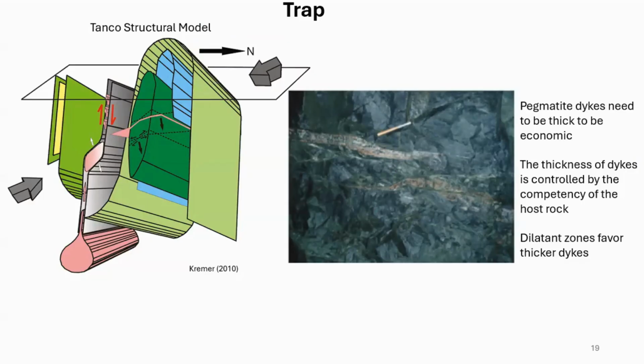We have structural traps. So this is a model of Tanco that Paul Kramer did. We can see these nice en echelon dikes cross-cutting a gabbro raft in Tanco, and the model is that it's transpressional and you're getting opening up in a particular band of the shear zone, similar to what we see as a dilatant zone in gold deposits. So there are a lot of structural similarities between gold deposits and pegmatites, they're not identical. We're out there looking for dilatant zones because the dilatant zones are where the thicker dikes are going to be.